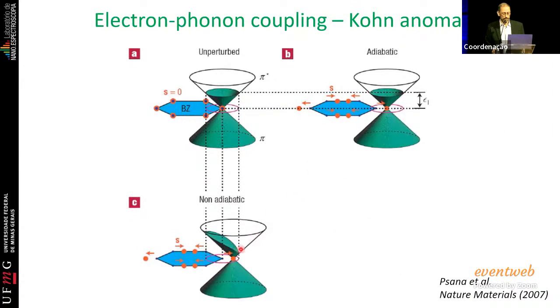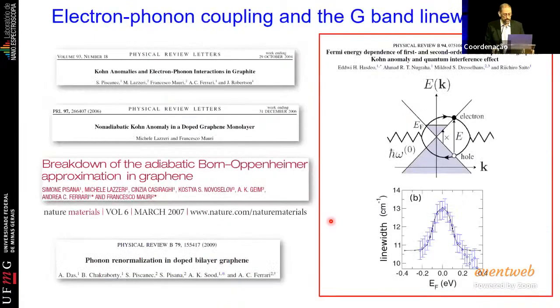They said, what happens is very much like if you are shaking a glass of wine, okay? Because the electrons respond very fast to the phonons in the graphene structure, when the atoms move, the electrons are not static, they are not stable. And these generate a very strong electron-phonon coupling. And you cannot treat electrons separate from phonons. So this has been studied by many groups, both theoretical and experimental.